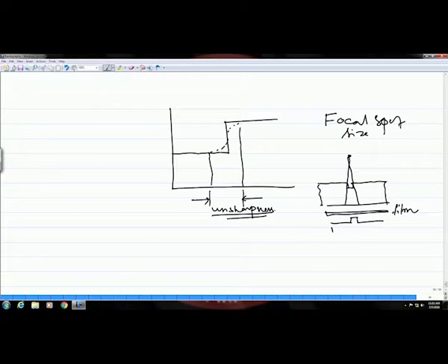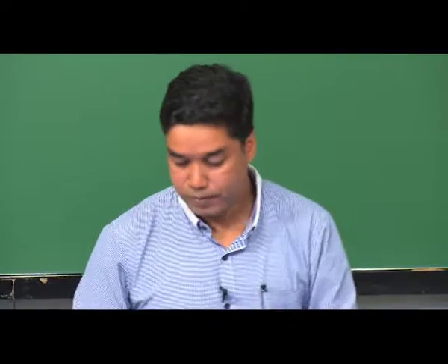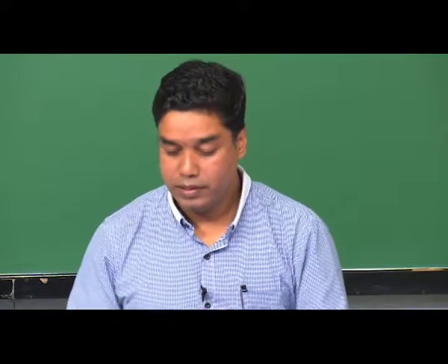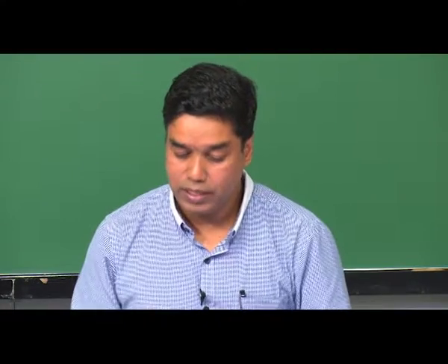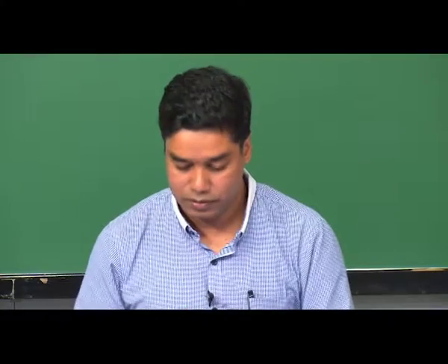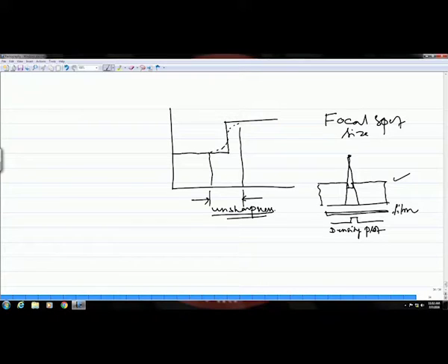So, this is actually the density plot that you see on the image, because you are collecting the photographic density from different parts of the object, and that is what is being shown on the X-ray film image as contrast. Okay. So, if it is a point source, there is no difficulty in reproducing the boundary of an object, as you could see here. But if it is a finite size source, then because of that given size, it will act as multiple sources.